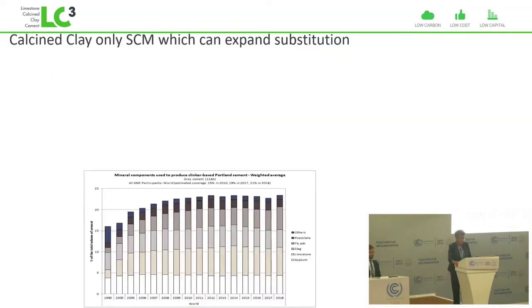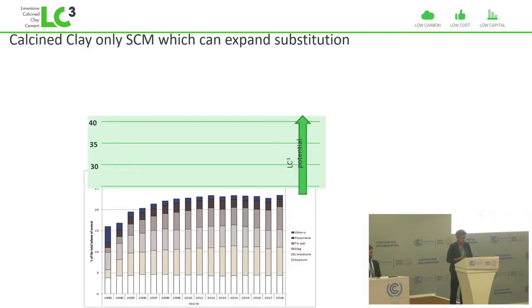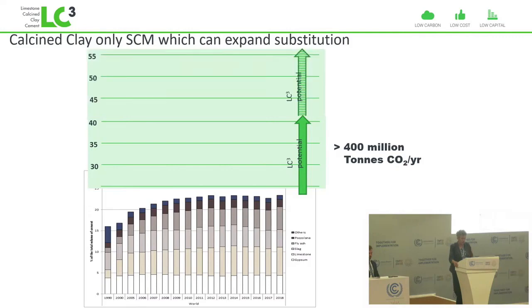And so coming back to the potential, well, this graph here shows the current levels of substitutes today, and this has stagnated at around 20% for the last decade or so. Now, when we remove the limitation that I told you about at the beginning from the availability of slag and fly ash, then we can certainly go to a much higher level of substitution, such as 40%, which would be equivalent to saving 400 million tons of CO2 per year. And that's like about 1% of the emissions worldwide today with just one single technology.